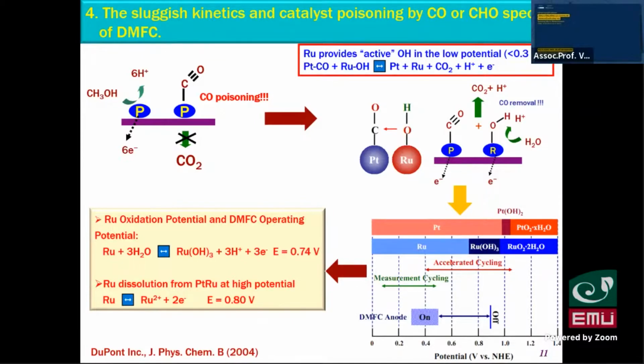So they use a second method, very famous - ruthenium along with platinum. We can see from the reaction here: when we mix ruthenium with platinum, the ruthenium can provide active oxygen species at low potential, below 0.3 volts. So the CO poisoning platinum will be released to form CO2, and we can match the potential here.